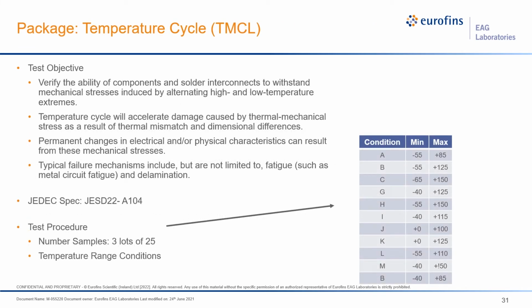Temperature cycling. The temperature cycling verifies the components and solder interconnects are capable of not being damaged with alternating high and low temperatures. The temperature cycling may induce mechanical failures such as cracking, delamination, and warping in the package. Temperature cycling is a non-biased test. There are different classifications for the temperature range and the number of cycles to be performed. Condition B of minus 55C to plus 125C for 700 cycles is the most common. Following the temperature cycling, the device must be electrically tested to verify that it's fully functional and meets all its specifications. You may refer to the JEDEC spec for more details on temperature cycling.